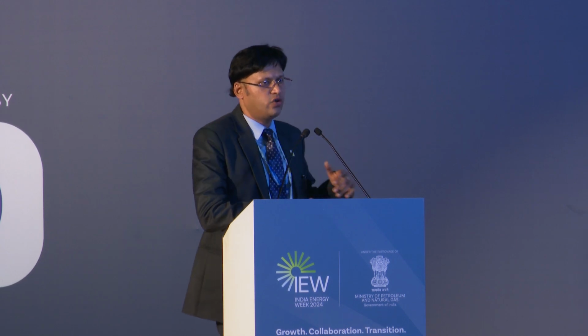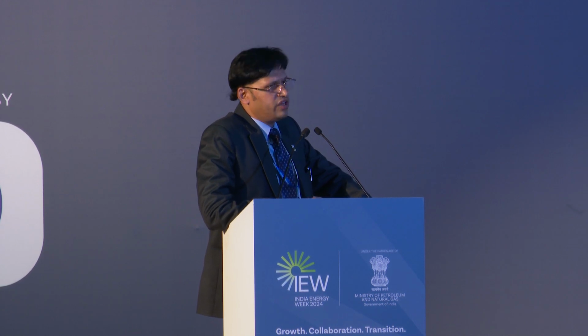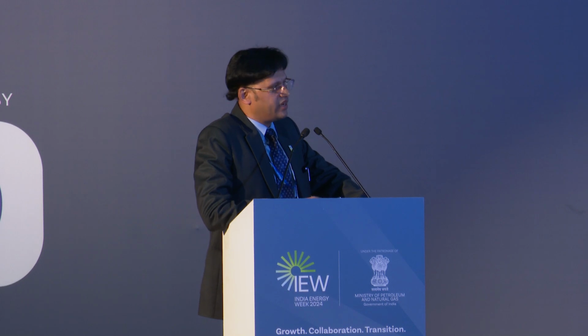And on the reverse side, if you have a tube bundle reactor wherein your metal hydride is filled in the tubes and your heat transfer fluid is going into the shell, and then again we see how the hydrogen is getting absorbed, then we did the reaction. Although the weight percent is on a lower side, in subsequent experiments we got a higher weight percent. But you see that the embedded cooling tube has slightly better performance as compared to the tube bundle. But filling of the metal hydride in this arrangement is tough, because this is the only way to fill the metal hydride and to remove the metal hydride.